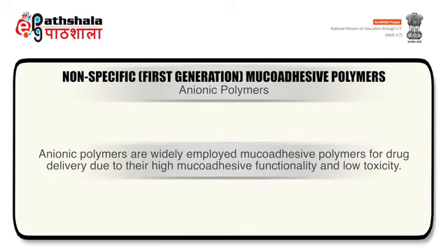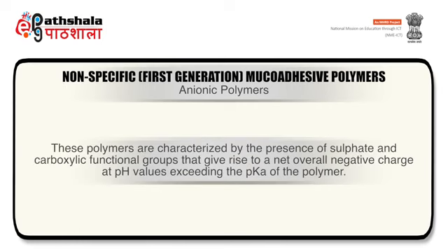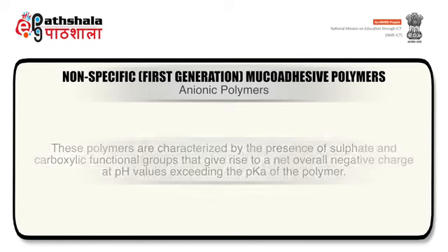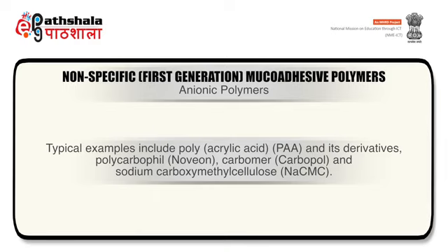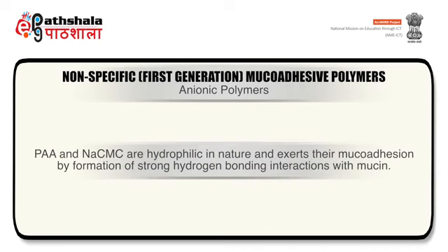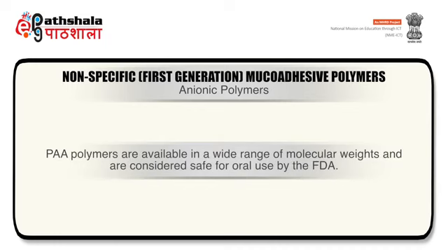Anionic polymers are widely employed mucoadhesive polymers for drug delivery due to their high mucoadhesive functionality and low toxicity. These polymers are characterized by the presence of sulfate and carboxylic functional groups that give rise to a net overall negative charge at pH values exceeding the pKa of the polymer. Typical examples include polyacrylic acid and its derivatives, polycarbophil, carbomer, and sodium carboxymethyl cellulose. Polyacrylic acid and sodium carboxymethyl cellulose are hydrophilic in nature and exert their mucoadhesion by formation of strong hydrogen bonding interactions with mucin. Polyacrylic acid polymers are available in a wide range of molecular weights and are considered safe for oral use by FDA.